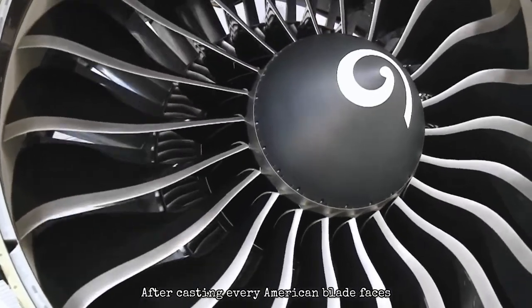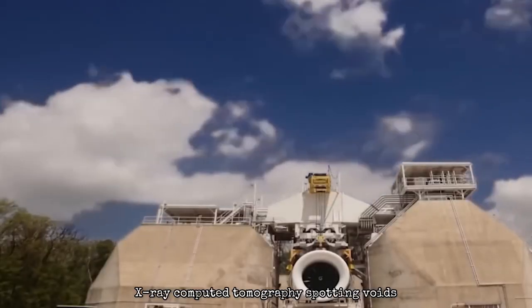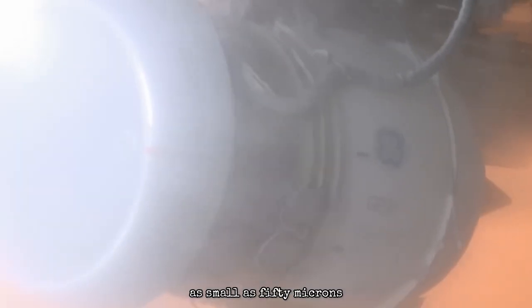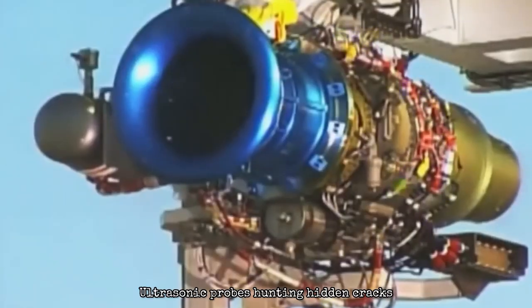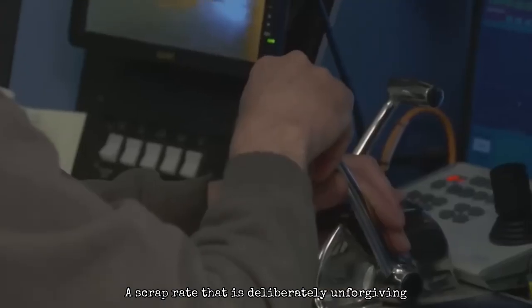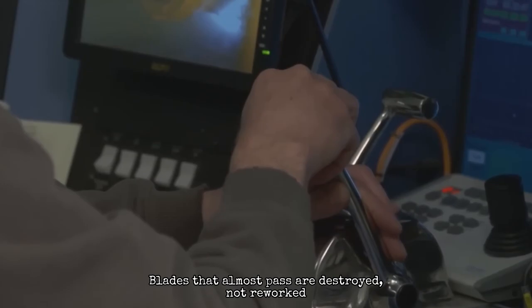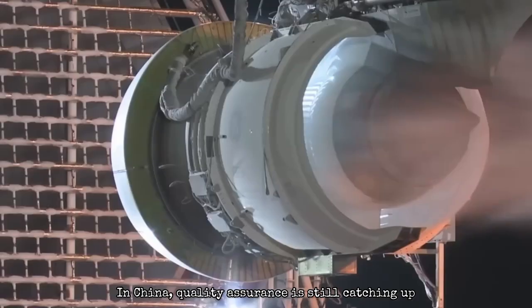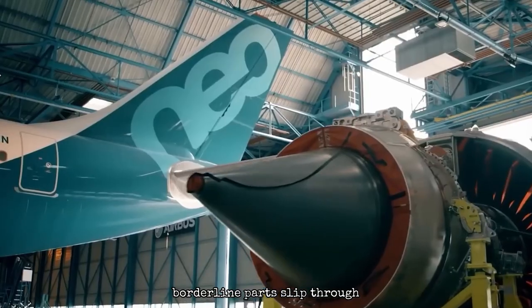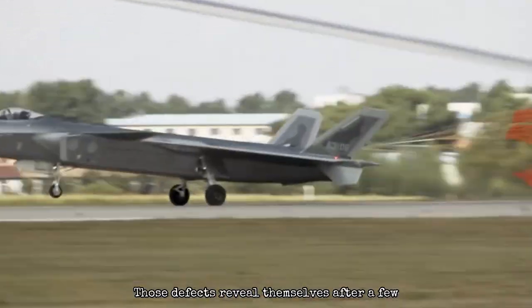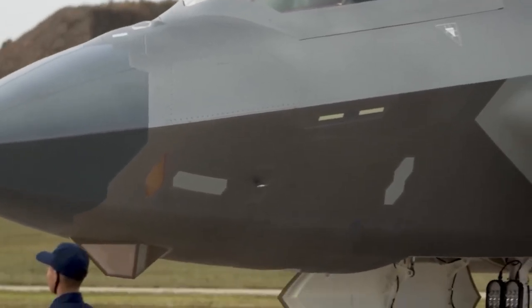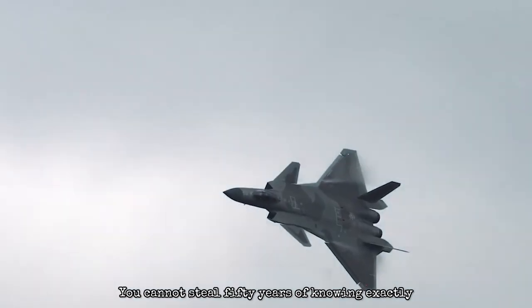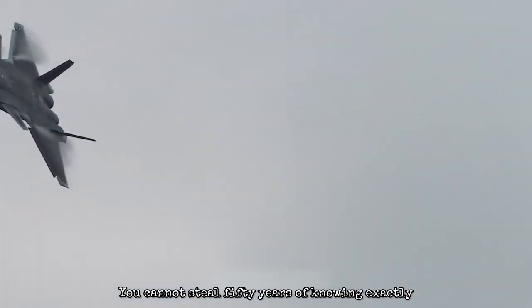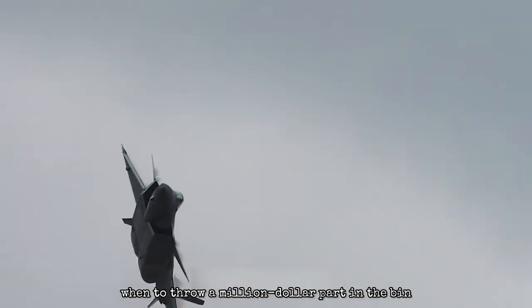After casting, every American blade faces X-ray computed tomography, spotting voids as small as 50 microns. Ultrasonic probes hunt hidden cracks. A scrap rate that is deliberately unforgiving. Blades that almost pass are destroyed, not reworked. In China, quality assurance is still catching up. The pressure to deliver engines on time means borderline parts slip through. Those defects reveal themselves after a few dozen hours at full throttle. You can steal a blueprint. You cannot steal 50 years of knowing exactly when to throw a $1 million part in the bin.